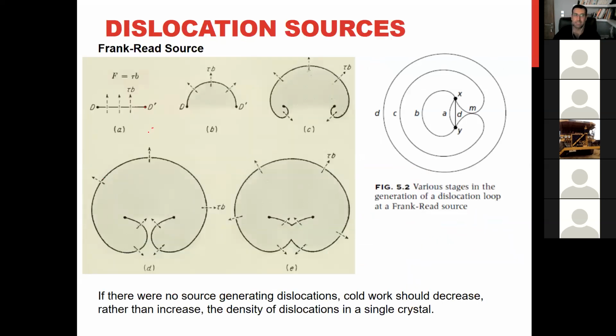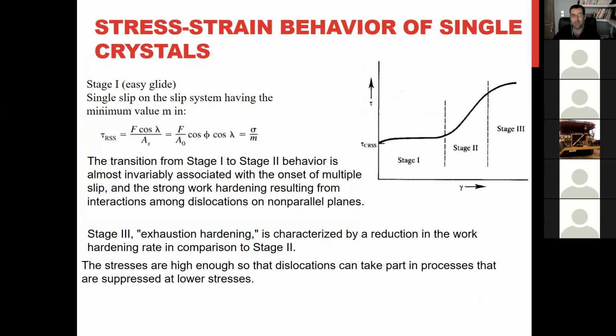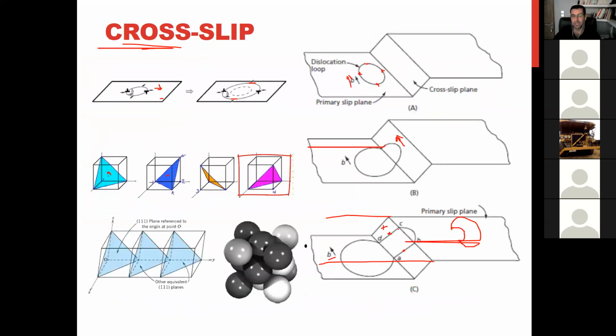It means this plane is that plane that dislocation can move. Edge dislocation and screw dislocation both can move, but these 2 points cannot move. This dislocation, this line of dislocation, which is coming from another plane, exactly in these 2 points cannot move. Why? Because if it's moved, it means you are moving this part also in this plane. It's not possible because this plane doesn't allow this dislocation move. So we have here 1 point, and here we have 1 point. That dislocation in this place is locked.